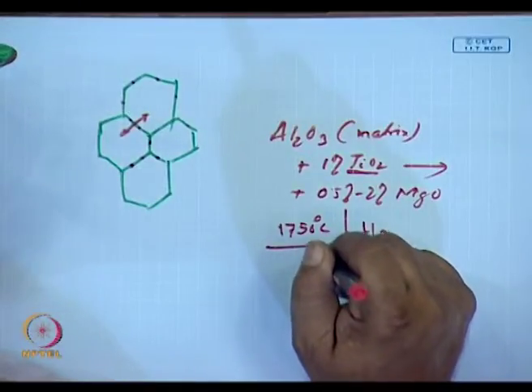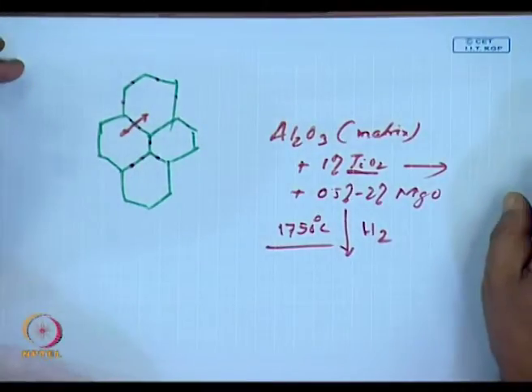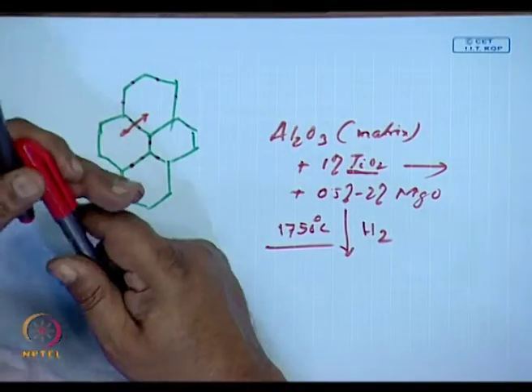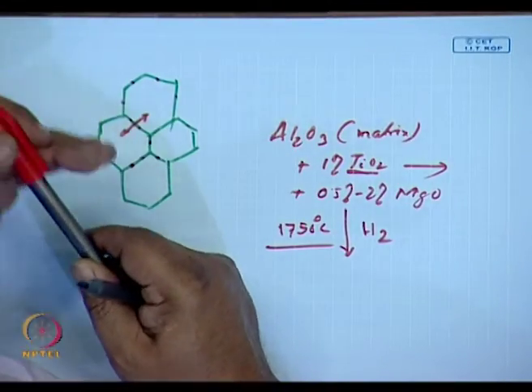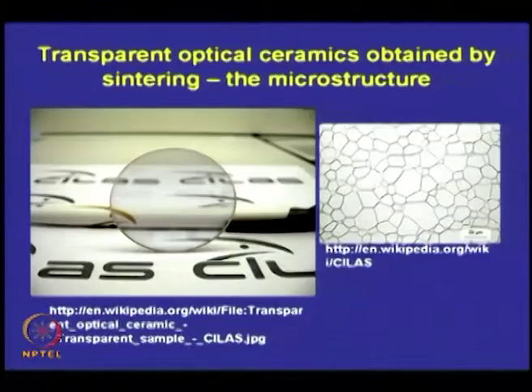Otherwise, it would have required at least 200 degrees centigrade more temperature to sinter the alumina, in which case even the presence of the grain growth inhibitor would not have been sufficient to stop the grain growth in this particular microstructure. So we required a balance of low temperature, sufficient sintering aid which would abstract the oxygen, and a grain growth inhibitor.